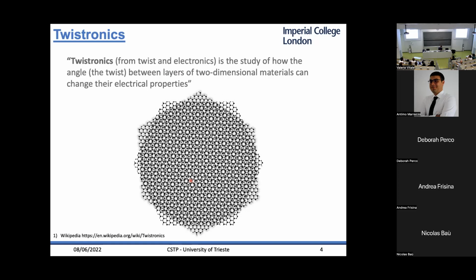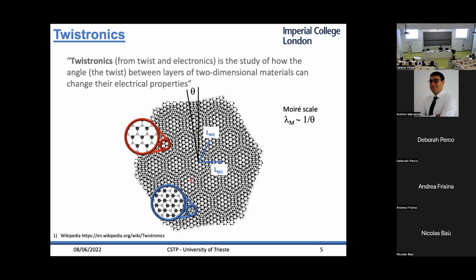And as you can see, a pattern emerges at different angles. For example, at this particular twist angle, which is roughly 10 degrees, you can see an emergent pattern, which is called a Moiré pattern. You have regions where the two layers are in AA stacking. For example, if these are two layers of graphene, this is carbon on top of carbon. And then there are regions with AB or Bernal stacking, where the carbons of the bottom layer are in the middle of the hexagon of the carbons of the top layer. You have these alternating stacking regions, and also some other stacking in between.